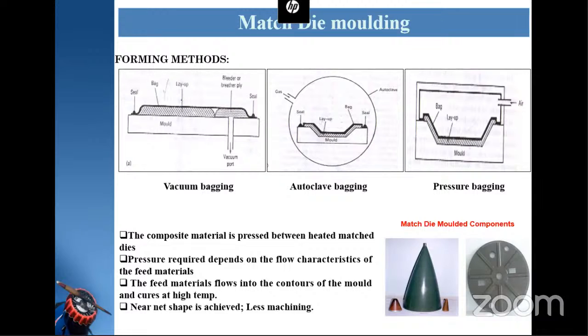Suppose in metal, if you want to make this type of cone, you have to make the sheet and then cut it into the shape, and then roll, bend and then weld. But unlike in metals, in composites, if we have the mold, we can place the fibers and put in both male and female molds, and you heat, and you get the final component. So there is no machining. Near net shape components you are able to get. You can see another plate which has ribs on both sides, which is also made in one go without any machining. Only edge trimming is done to realize the final component.